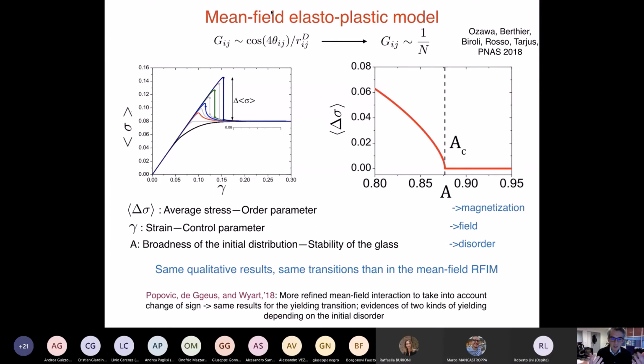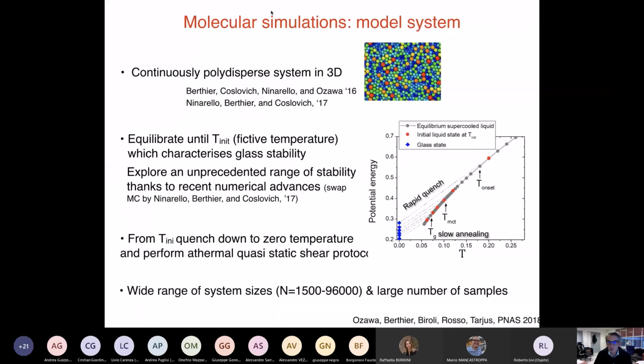And it really seems that the way in which an amorphous system yields is different depending on the degree of disorder. And there are really 2 phases, and these 2 phases are separated by a critical point. So while this is mean field theory and the others are simulations, and all this is for an elastoplastic model, so it's not the real system, now that we have positive results, it's good to go to real simulation and see whether the effect is there or not.